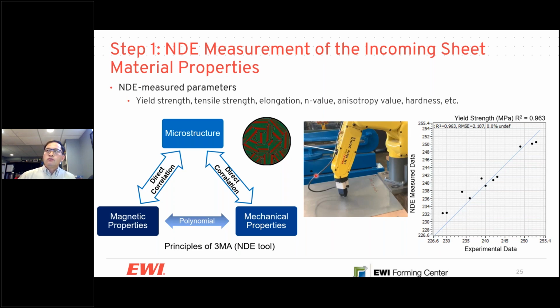The first case study is how we can control or reduce necking, cracking and wrinkling in the stamping process. First, we are using a non-destructive sensor, which we call an NDE sensor, non-destructive evaluation sensor. When the material properties change, meaning the microstructure changes from coil to coil from the steel mill, those microstructure changes also influence the magnetic properties. So by measuring the magnetic property with this NDE sensor, we can determine the change in mechanical properties.